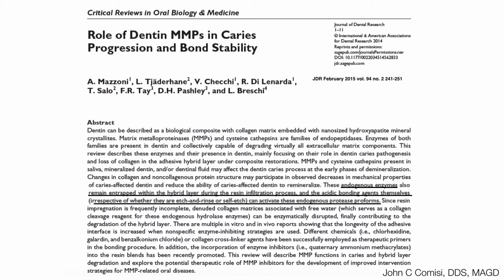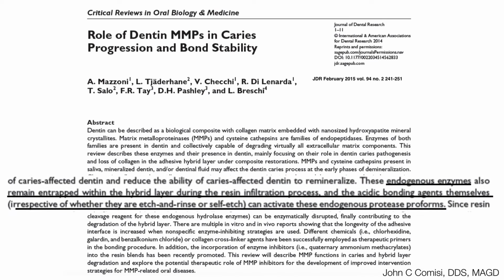To add to the complexity of dentin adhesive bonding, this Journal of Dental Research February 2015 paper by Mazzoni, Pashley, Tay et al., entitled The Role of Dentin MMPs in Caries Progression and Bond Stability, brings out the fact that endogenous enzymes remain entrapped within the hybrid layer during the resin infiltration process, and the acidic bonding agents themselves, irrespective of whether they are etch-and-rinse or self-etch, can activate these endogenous protease proforms.